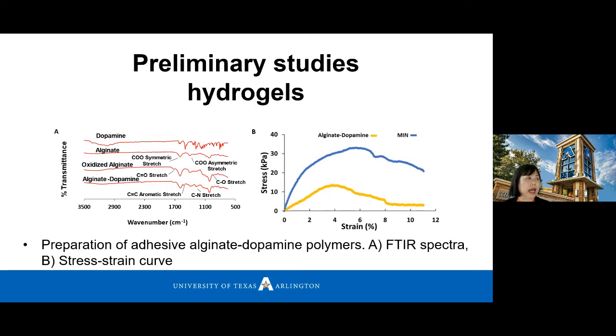For our preliminary study, we developed the adhesive alginate dopamine polymer, and you can see from this that when you incorporate dopamine with the hydrogel called alginate, we can see the C=C aromatic stretch and also the peak of the dopamine. We also found that the alginate dopamine and our nanocomposite material is stronger compared to the alginate hydrogel alone.